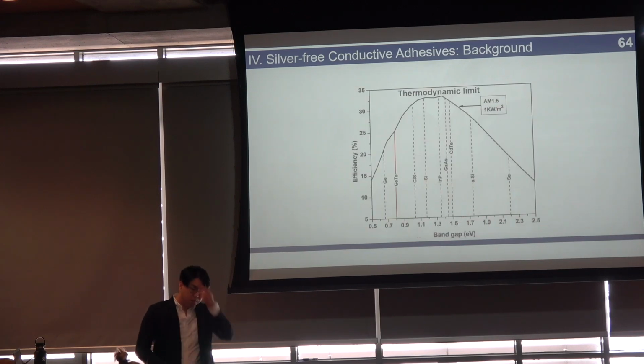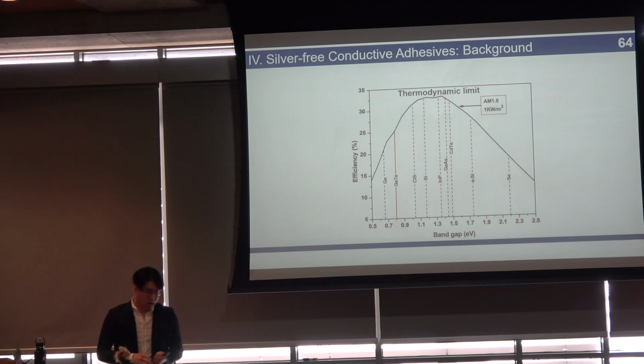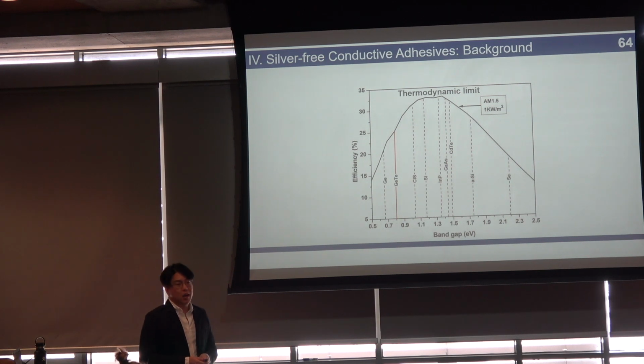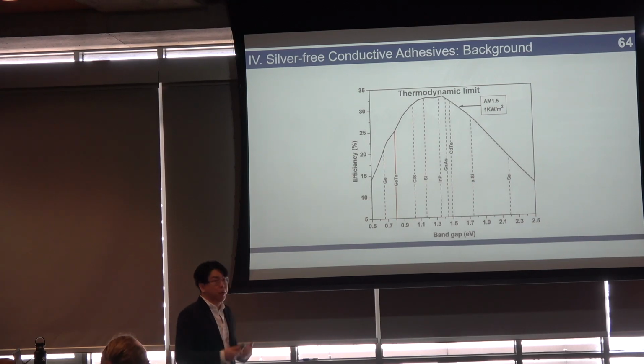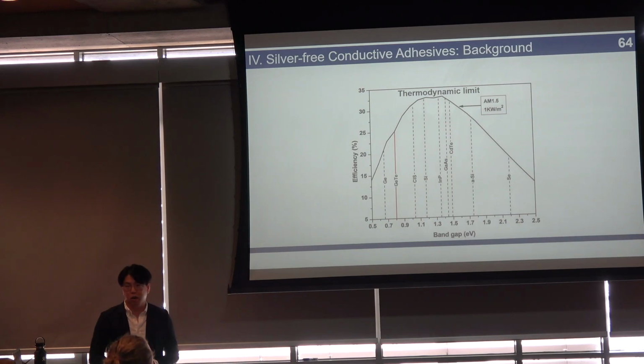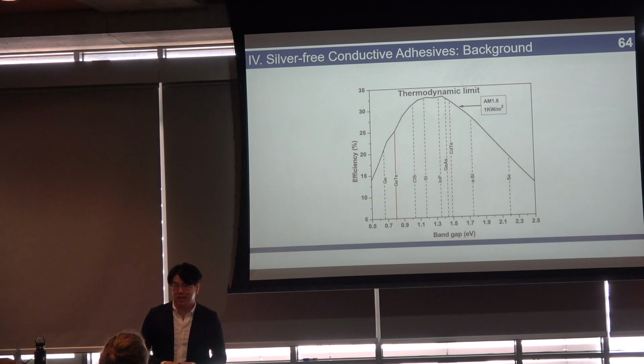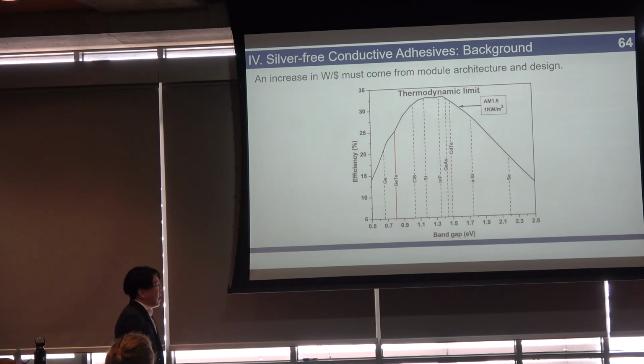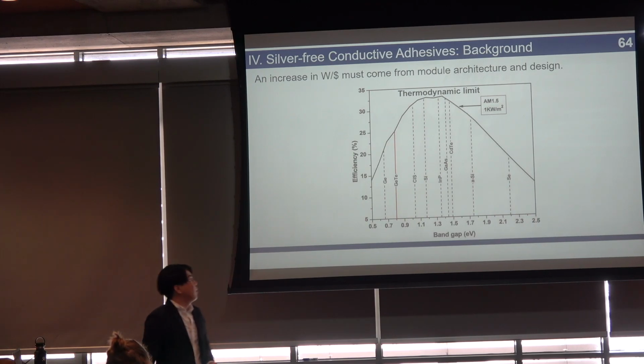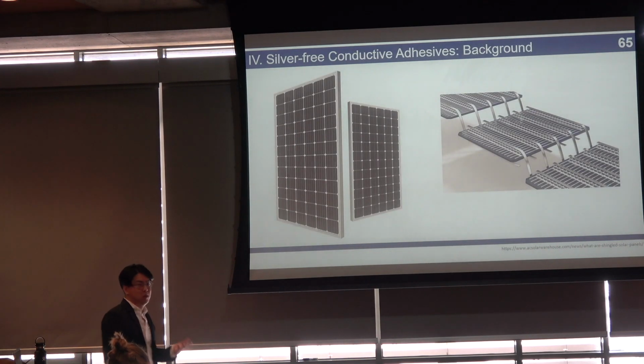So why is this? It turns out that for any sort of material, there is a thermodynamic limit for how efficient your device can be made. For silicon, this is about 33%. And considering for commercial cells, we're already at about 25 to 27%. We're already pretty close, right? So this means that any sort of increases in efficiency or decreases in price generally have to come from module architecture and design. So this is what a modern solar cell looks like.